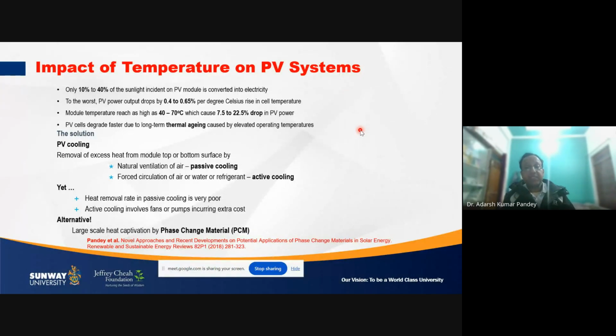At that time, what happens? The temperature of the PV panel goes beyond 25. It depends on the season. Especially if you talk about Uttar Pradesh or Rajasthan, temperature may go roughly around 48, 50 degrees centigrade. So there is a temperature difference of 20 to 25 degrees centigrade. The PV power output drops 0.4 to 0.65% per degree Celsius rise in the cell temperature. So you can imagine how much power output drops when the temperature is 50 degrees centigrade.